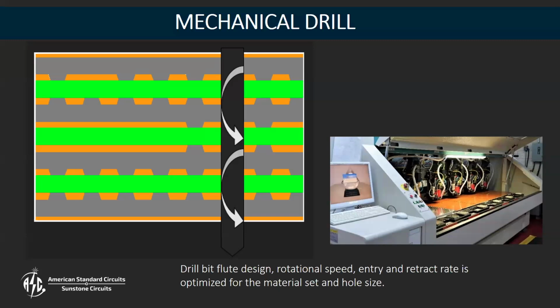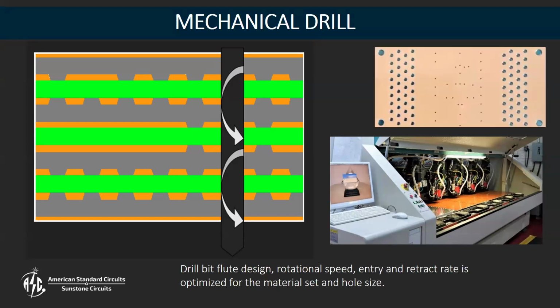So having a hard phenolic layer there at the bottom allows us to get that nice smooth drilled hole all the way through the part. And that's what we're looking at there, drilled holes now on the copper layer, which is going to be layer 1 in our case.